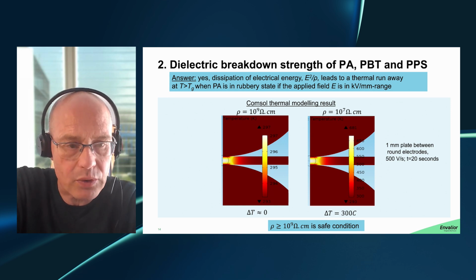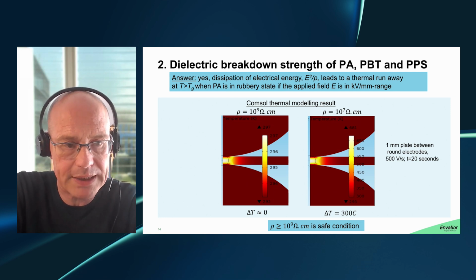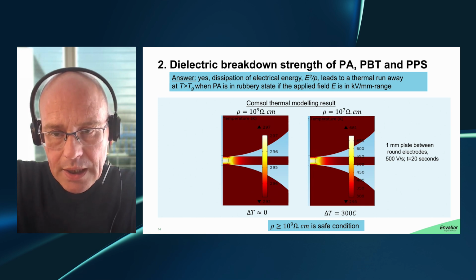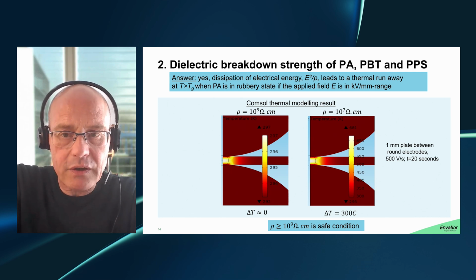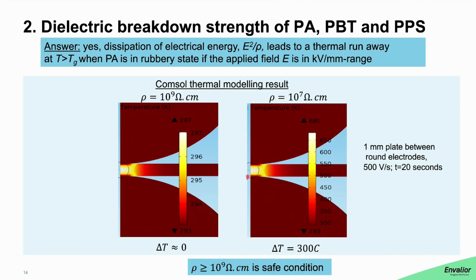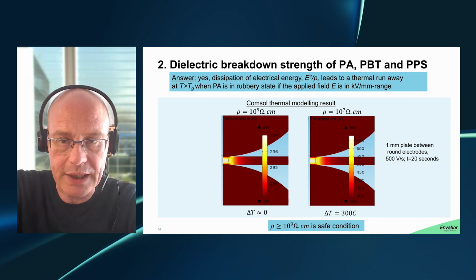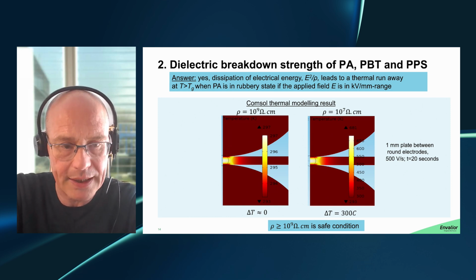For the calculation on the right, it was 10 to the power 7 ohms times centimeter, a value that you can encounter for a polyamide at temperatures above the glass transition temperature. Now, because of that finite resistance, there is a current flowing in between these electrodes here, and that may then lead to a resistive heating or a heat up of your material. And if the current is high enough, it can lead to a thermal runaway and a local breakdown.